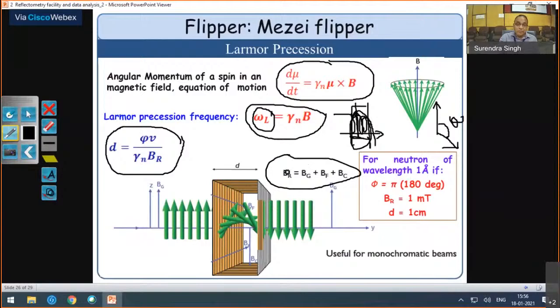So the total field is Br. Br is nothing but Bg, this is the guide field, plus Bf, which is the perpendicular field required to flip the neutron, plus Bc. Bc is opposite to the guide field. The same 20 Gauss you have to apply, because you have to cancel out this Bg. So effectively you have only the Bf field, because Bc is nothing but minus Bg. Okay, so using this equation, you will be able to get this.